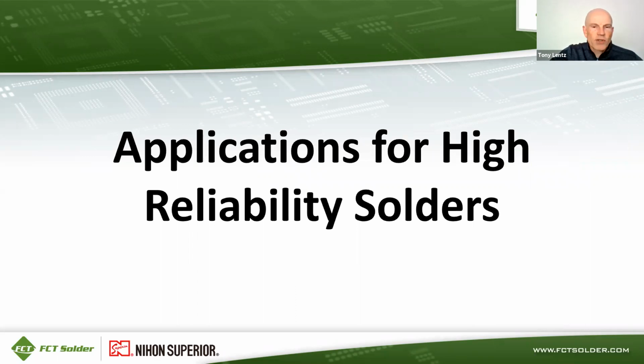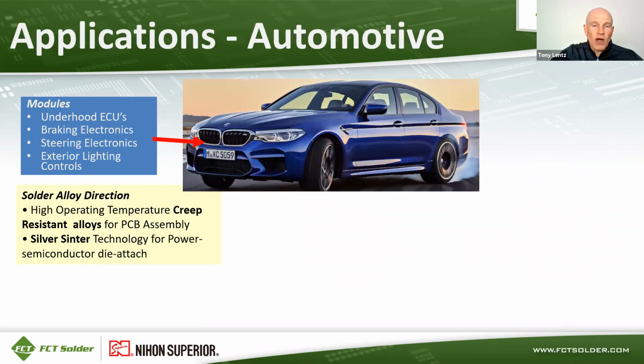What are some applications for high reliability solders? Of course, automotive provides a huge opportunity for high reliability solders, especially under the hood. So the modules that are using solder alloys are electronic control units, braking electronics, steering, and the exterior lighting controls. And the typical direction in the industry for solder alloys is using alloys that can hold up to high operating temperatures and that are also creep resistant.